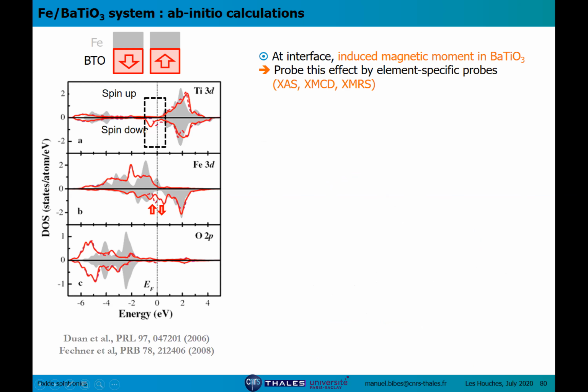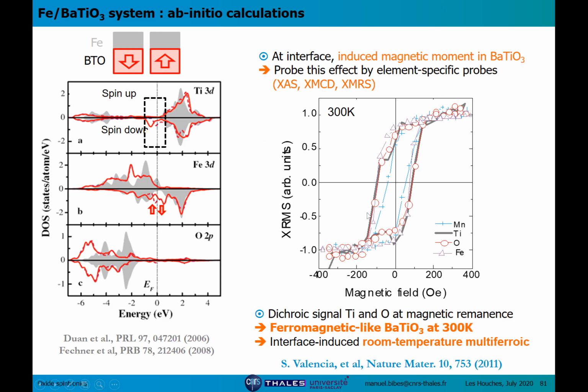There's another consequence of this, and it's also in the prediction by this paper by Evgeny, is that at the interface, titanium is going to acquire a finite spin-dependent density of states, which should result in an induced magnetic moment, which we also observed using XMCD and XRMS measurements at BC. So you can see here the gray curve is a hysteresis curve at room temperature of the titanium moment. So in these devices, we not only have ferroelectric control of spin polarization and TMR, but also interface-induced multiferroicity at room temperature.